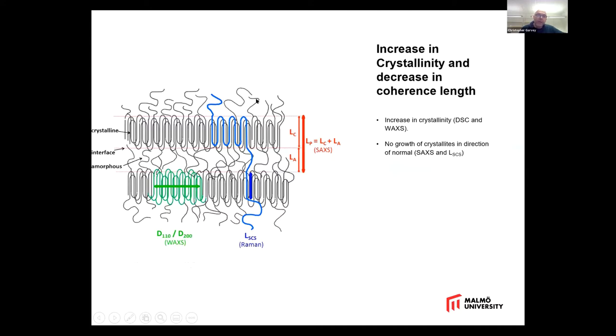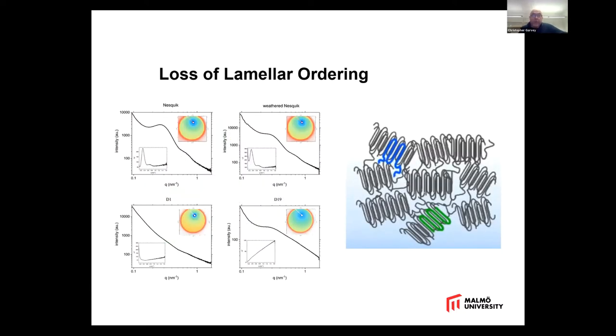Interestingly, it doesn't grow in this direction. What we see is small crystals nucleate in here. What we also see is this lamellar structure is disrupted. So very well-defined physical changes in the material. Small angle scattering is probably